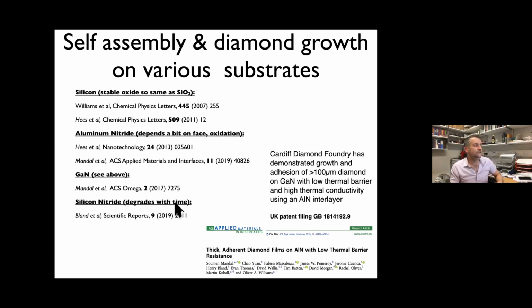Silicon nitride is an interesting case because the problem with silicon nitride is, if you leave it on the bench, the zeta potential degrades across time. So we spotted that about a year ago in Henry's paper. It's a commercial company actually, and basically what happened is that their seeding went bad, and then you measure it with the streaming potential, and you can see that the surface is just getting contaminated. So if you immediately flash the surface just with an oxygen plasma, all of a sudden it works again. So that's what this paper is about here.